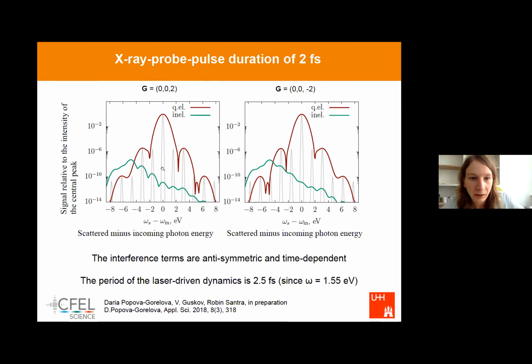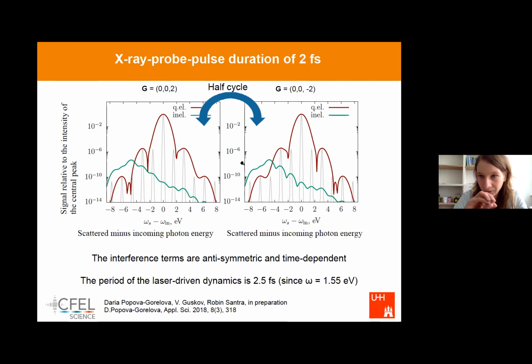And what happens is that in gray lines you see the original side peaks. As the X-ray probe pulse duration becomes shorter, these side peaks become broader and broader, and then start to overlap. And overlap means that they start to interfere. What we find out is that as soon as they start to interfere, they stop being centrosymmetric. So it means that for scattering vector 002 and scattering vector 00-2, the signal is now different. And if we shift the time by a half cycle, then they also switch their positions.